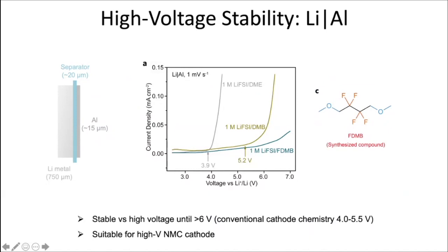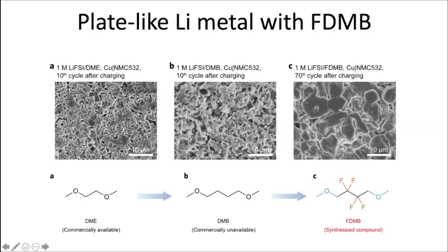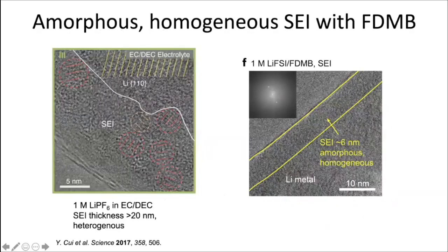And in terms of the voltage stability, we observed that the FDMB can achieve significantly higher stability compared to the other previously reported solvent, as we expected. And then in terms of the lithium metal growth, you can also see that the growth morphology is significantly changed. In the case of FDMB, we see more plate-like growth, while in the other two solvents, which tend to have instability in chemical reaction with the lithium metal, you would see those dendrite-like growth of lithium metal.